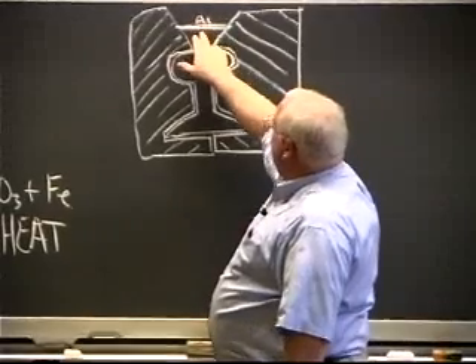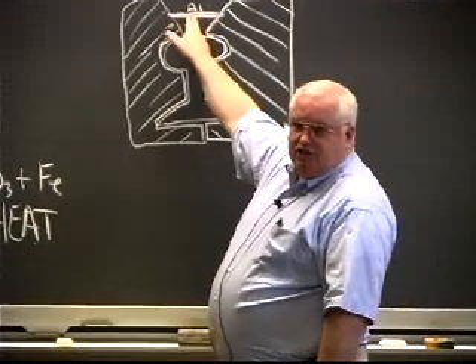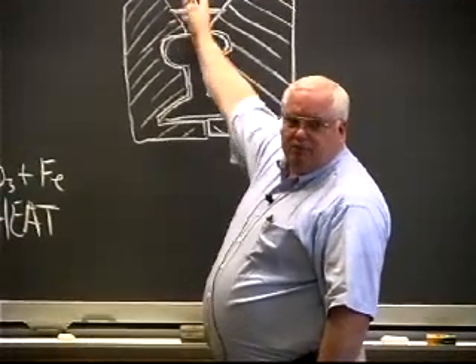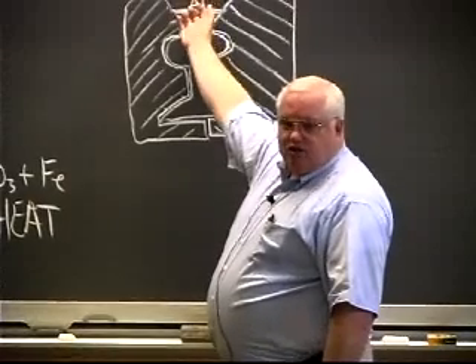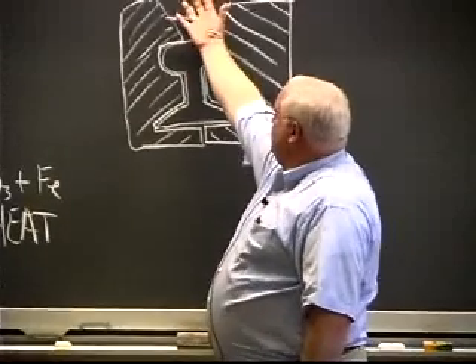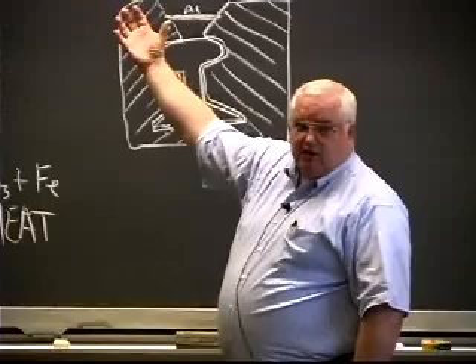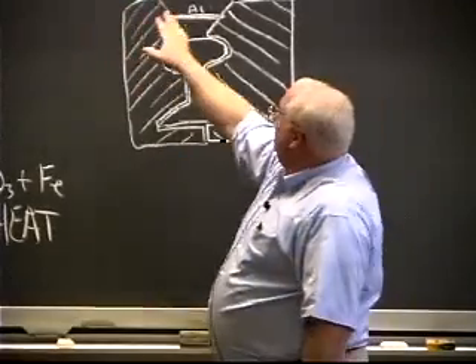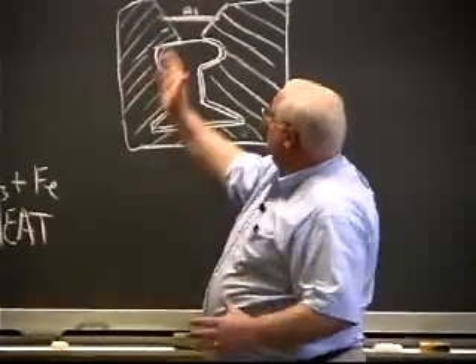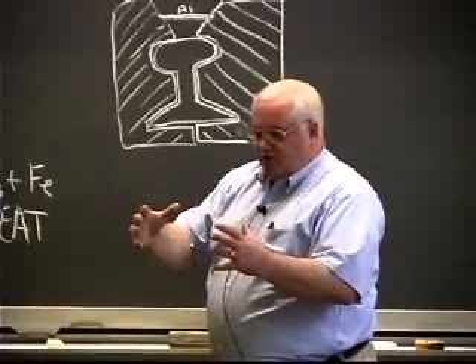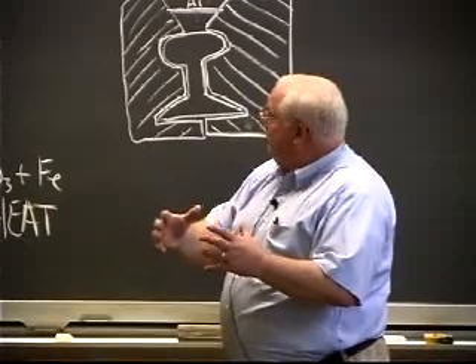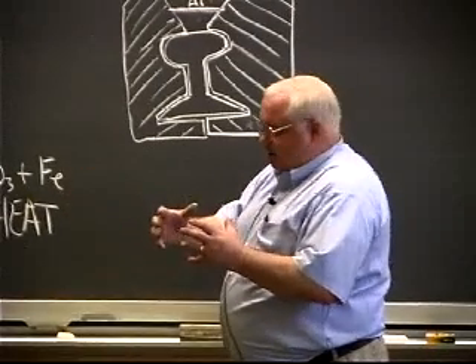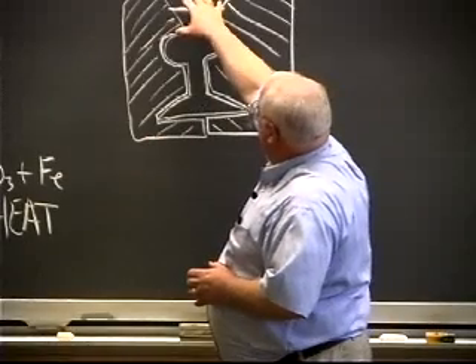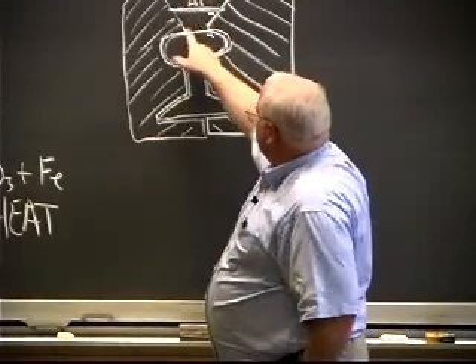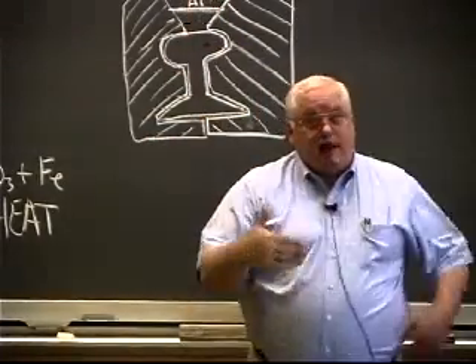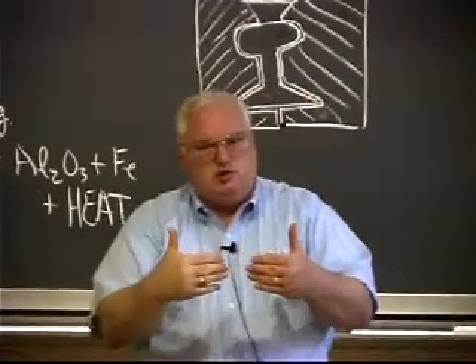The molten iron melts right through this little aluminum, because this is just a valve, just a sheet of aluminum. It keeps the sand up there when it's solid, but once the reaction goes and the iron starts forming, within literally 10 seconds this whole process is over. You've got this great big bucket of what looks like a sand reaction powder, and it all melts, and then the molten steel just melts its way through the aluminum and drops down into the cavity that you left between these two steel rails.